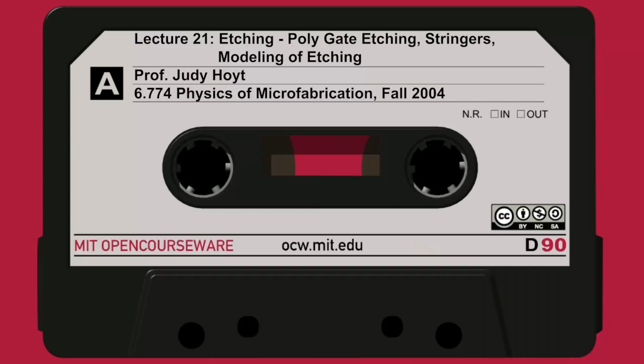Most etches, as we said, end up leaving a sidewall polymer that's either hydrocarbon based or it might be a glass-based, oxide-like material. That is what's responsible. Remember, it's the inhibitor layer that keeps you from etching sideways. That's what gives you such perfectly vertical sidewalls. You must have that inhibitor layer. The question is, what do you do with that inhibitor layer now that it's on your wafer? Every single gate has some goop, whatever it might be, sidewall junk, polymer, whatever you want to call it.